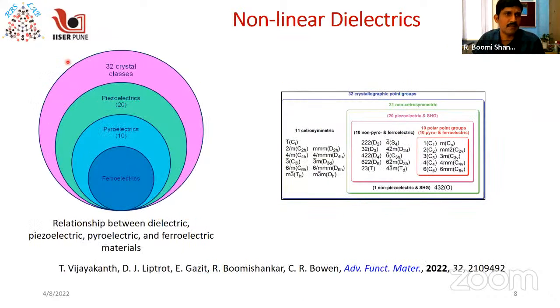Okay, so what we have understood so far is that there is a larger class of materials called dielectric materials. Piezoelectric will be a subset of the dielectric, pyroelectric will be a subset of piezoelectric, and ferroelectric is again a subset of pyroelectrics. Okay, and if you go back to the structure of the molecules or ions or salts or any material, the crystallography actually determines the nature of their electrical properties. If you look at the crystallographic tables, there are 32 crystallographic point groups, which contribute to 230 plus crystallographic space groups. Okay, so all those materials with all those space groups can potentially exhibit dielectric properties. If they are insulating in the first place, then they can exhibit dielectric properties. Therefore any material will be dielectric, but not all materials are piezoelectric.